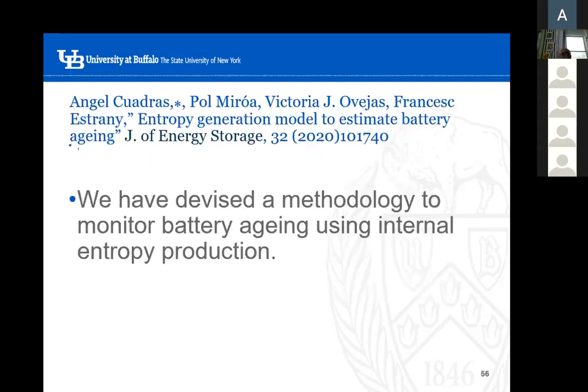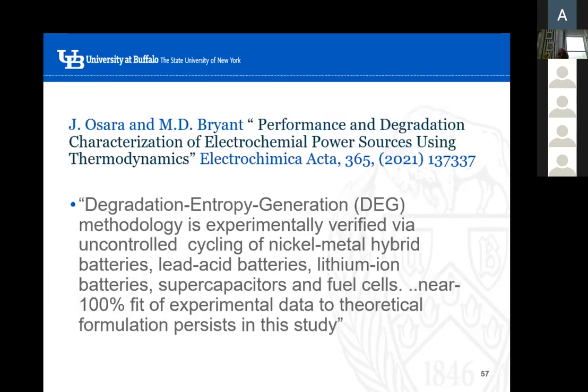This group is also from Spain. They use, again, the unified mechanics theory. They say we devised a methodology to monitor battery aging using internal entropy production. This group is from the University of Texas in Austin. They published a paper last year in Electrochimica Acta. They say degradation entropy generation methodology is experimentally verified via uncontrolled cycling of nickel metal hydride batteries, lead acid batteries, lithium ion batteries, supercapacitors and fuel cells. Near 100% fit of experimental data to theoretical formulation persists in this study.